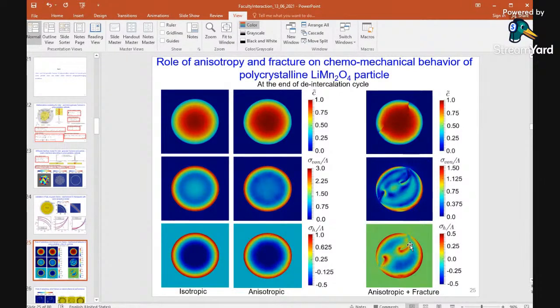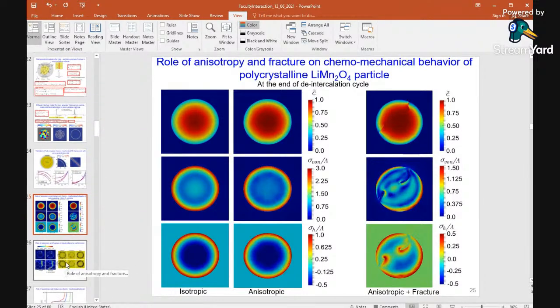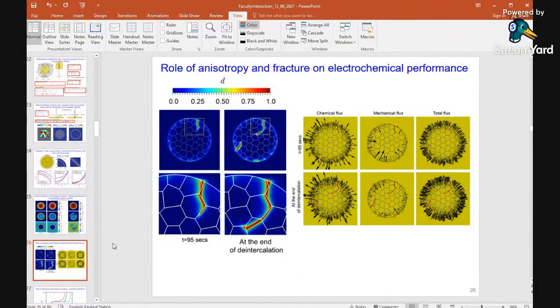It will try to pull the lithium towards the crack tip. So instead of allowing the lithium to go outside, it will hold the lithium if there is a crack. And that will interfere with your discharging process, because it is holding it. It is not allowing it to go outside, but that is necessary, because you want lithium to go inside and go outside reversibly without any hamper in order to sustain the proper capacity or cyclic capacity. So now I'll show how the crack is developed.